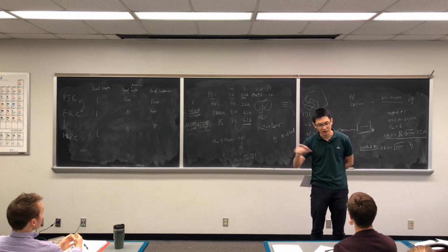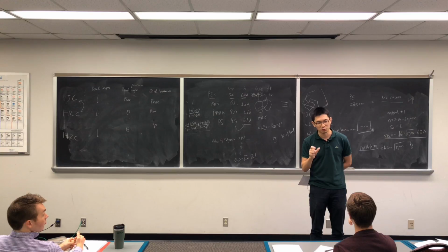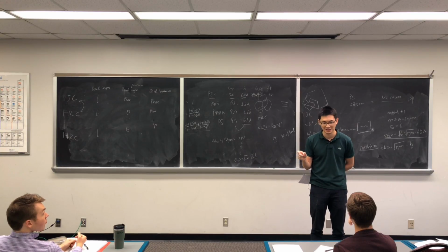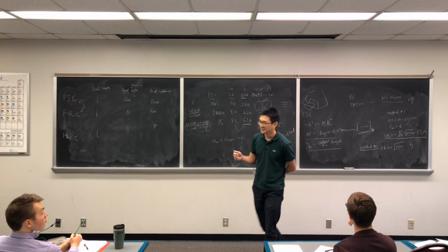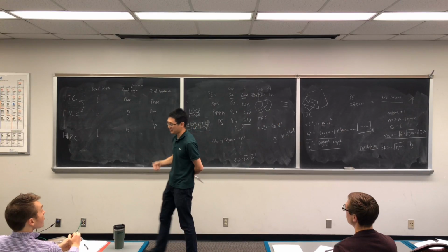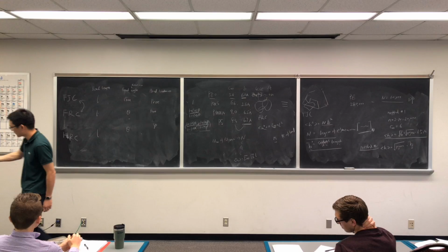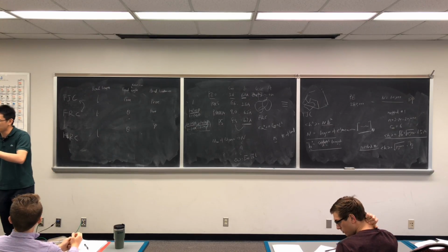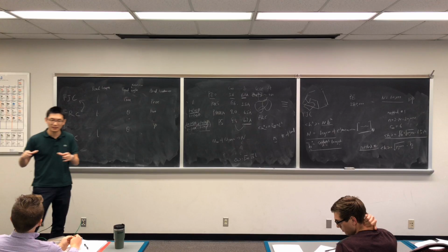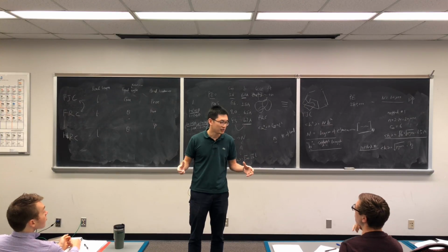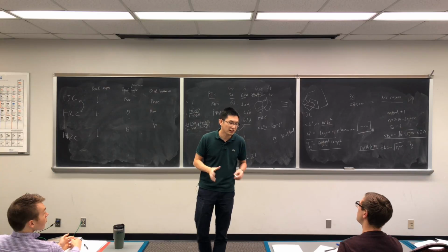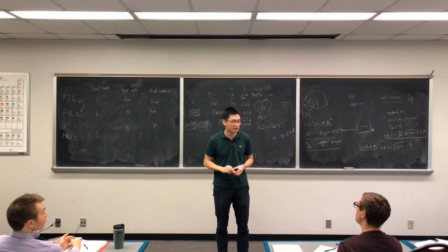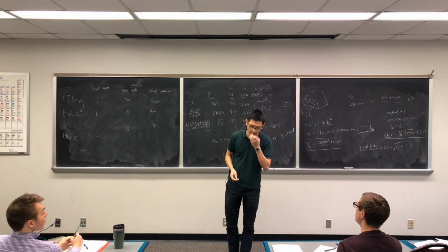So the other part, characteristic ratio, has one very, very important assumption: it will have relatively high molecular weight or degree of polymerization. Because in the last lecture, in the very last part, while we went through that very hard to chew entry, we omitted a second term in that expansion. And that omission was under the assumption that n will be very large. So 1 divided by n will be relatively small versus the other term, right? So C infinity works out if your chain is long enough, the molecule is high enough.